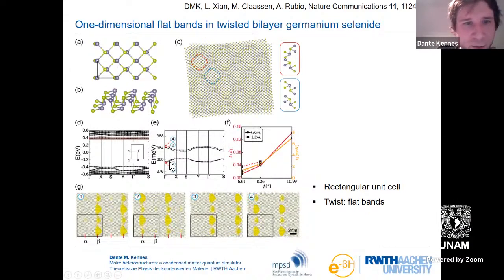And you see there's a bit of dispersion. The overall band is, of course, flat, but there's a bit of dispersion within this flat band. Now, if you go from X to S, along this direction here, you see that the band is almost perfectly flat. So there's almost no dispersion along the perpendicular direction. Then if you go from S to Y, along this direction here, you see again that there's a bit of dispersion. And then from Y to gamma, it's entirely flat again.